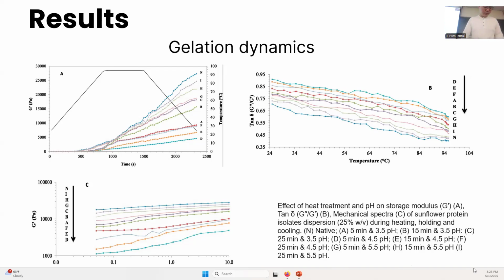It is attributed to the lower surface charge on protein molecules, which caused the formation of protein aggregates. At pH 3.5 and 5.5, the protein gel had a higher strength as compared to pH 4.5. The higher surface charge on protein molecules induces electrostatic repulsion between protein molecules, resulting in unfolding of protein molecules. Unfolding of protein molecules reduces the intramolecular interaction.